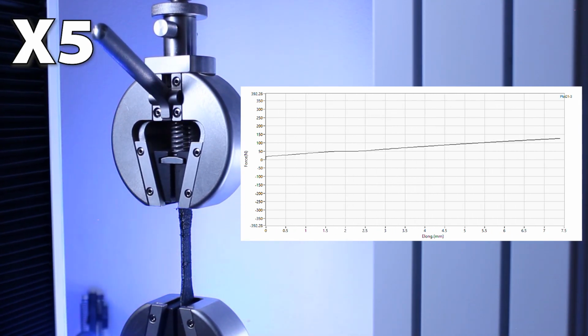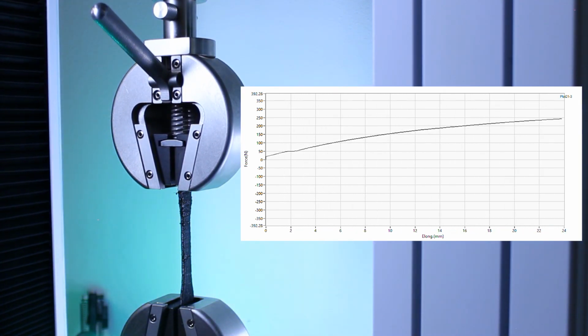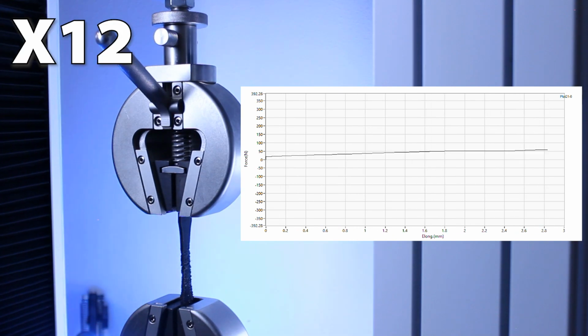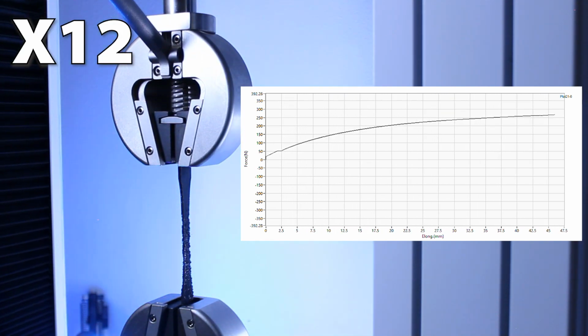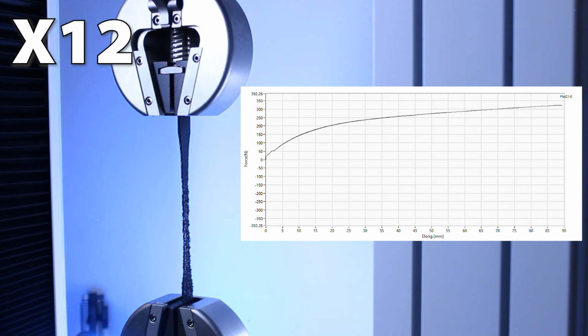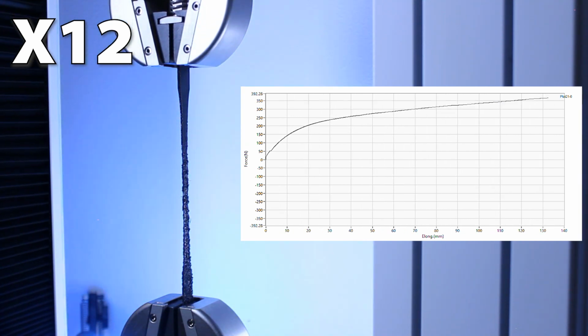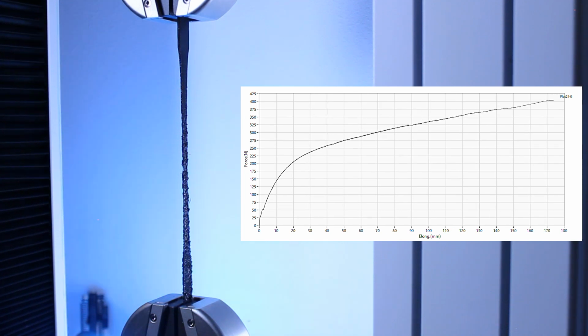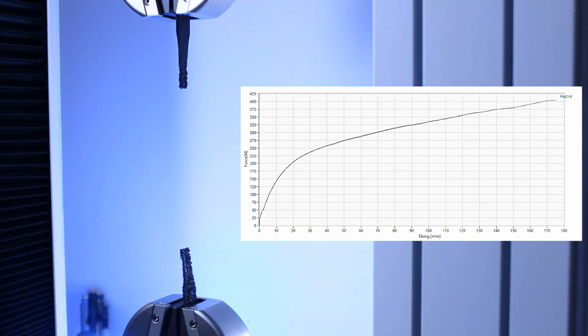So even though we got tests out of them, not all of them are as consistent as an ASTM test would be. So we have to redo this at some point. But again, this data is really useful as it is. Across all of these tests, we always ended up with a maximum force between 200 and 400 newtons. Now, that is on average about 70 pounds of force if you're over here in America, which is not a